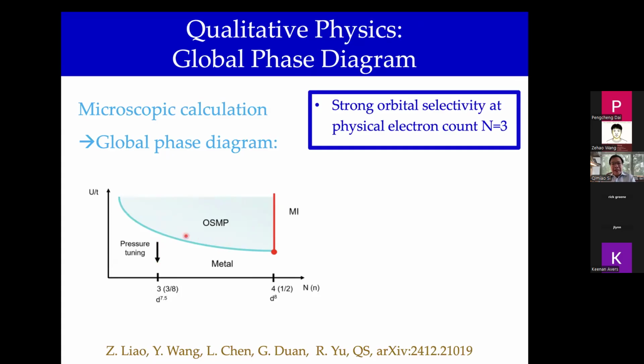And so the upshot is that there's the orbital-selective Mott phase sitting at sufficiently strong interactions, and for the relevant interaction range for the physical n equals 3 case, we're outside of it, but we're still experiencing the influence of the orbital-selective Mott physics as manifested in the strong orbital dependence of the renormalization effects. And so that's the qualitative conclusion, which we want to use to guide our own perspective about the physics here and the physics of the cousin materials.